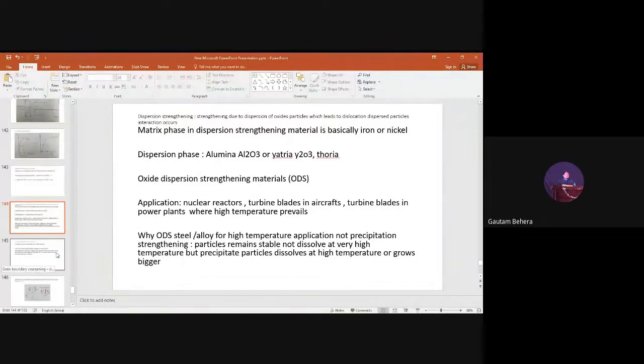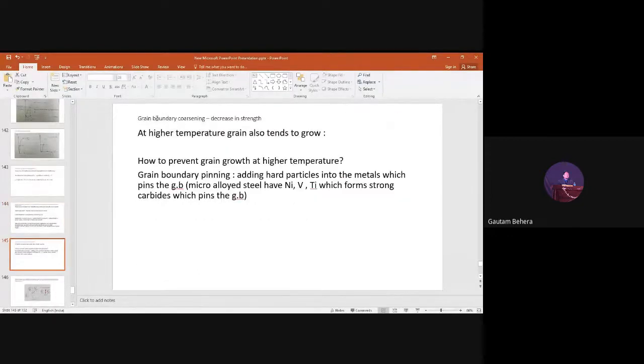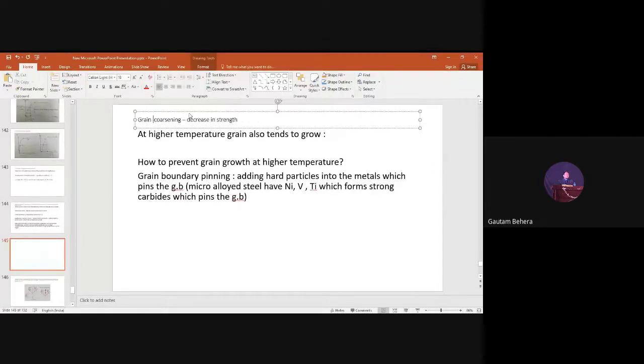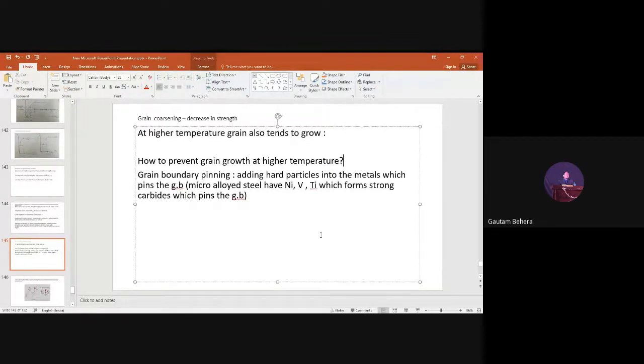So now another question is, what happens to the material at very high temperature? That is another point. Grain coarsening will occur. That means the strength will decrease, right? At high temperature, grains also tend to grow. So now the question is how to prevent grain growth at high temperature. If you have heard about microalloyed steel, we use a very small amount of alloying elements like vanadium and niobium, or titanium sometimes, right?